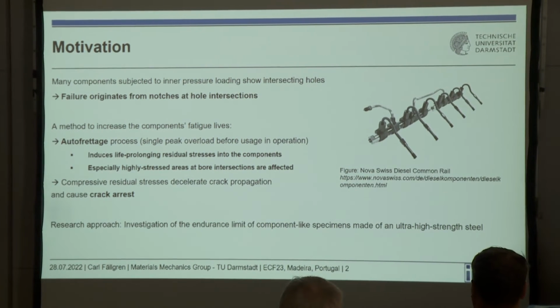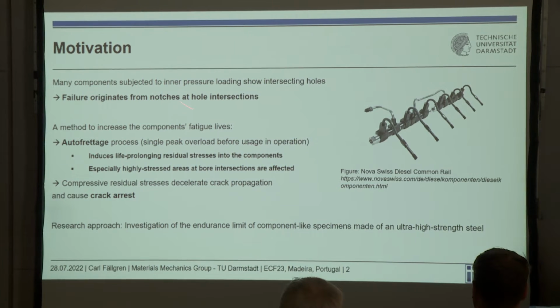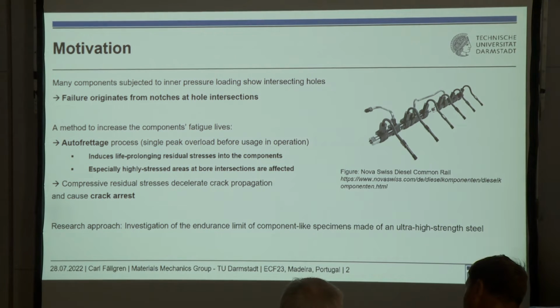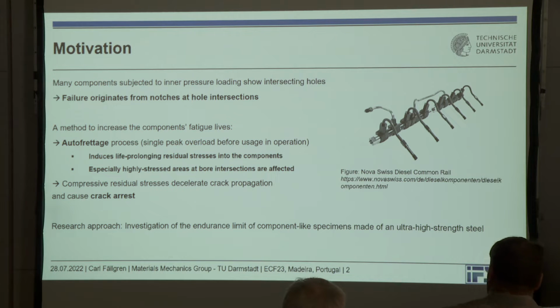And there's one method to increase the fatigue life of those components, and it's called autofrettage. Perhaps yesterday you heard some brief introduction about it. Autofrettage is a process which basically is a single peak overload before the component is put into operation, and that means you get plastic deformation on the inside. You induce life-prolonging residual stresses into especially highly stressed areas of those components. And those compressive residual stresses can decelerate crack propagation, and they can also cause crack arrest.